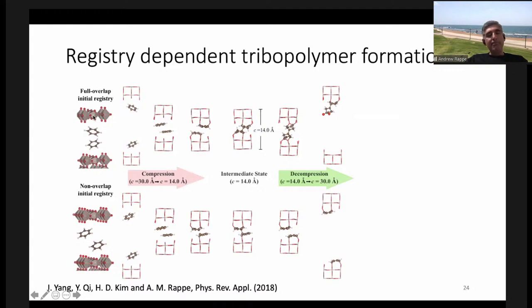Now we do the same methodology I described before, where we compress the bulk of the ruthenium oxide, then we let it relax, which transfers the stress onto the molecular system. And we have two different registries. The molecules could be right on top of each other, or they could be slanted. So they overlap partially, but not too much. And as we push them together, they come closer together, and again, we find a reaction.